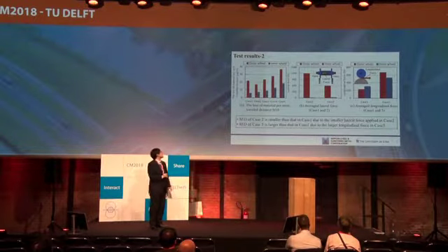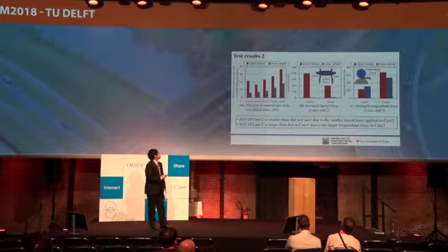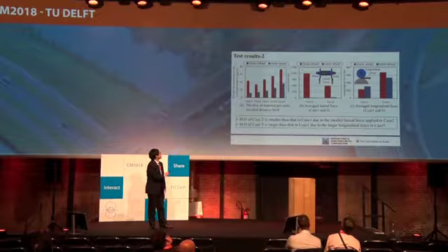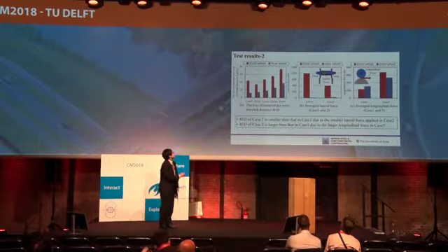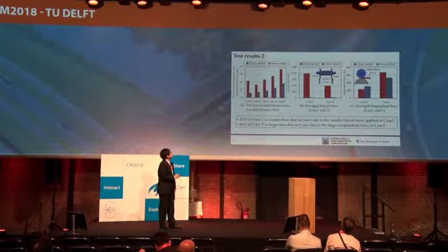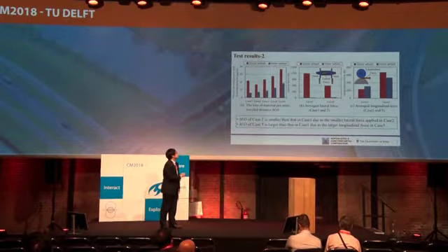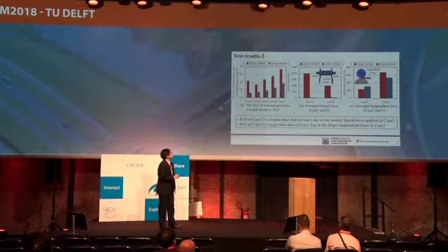For example, MSD of case 2 is smaller than that of case 1, because, as this figure shows, the applied lateral force of case 1 is bigger than that of case 2.